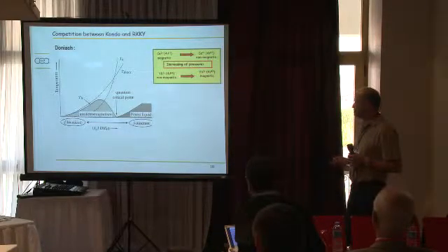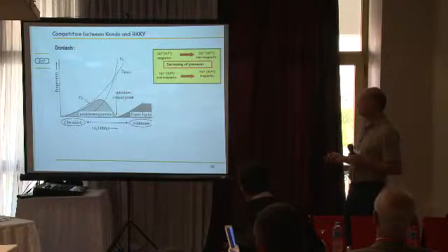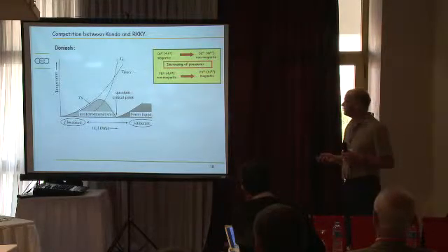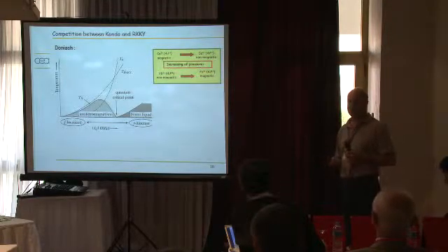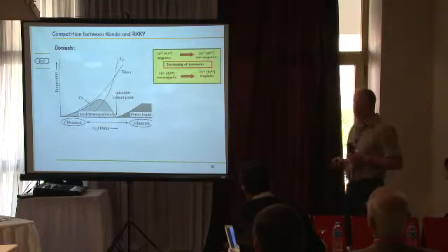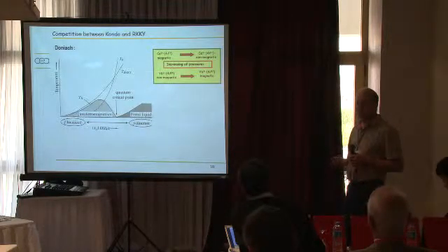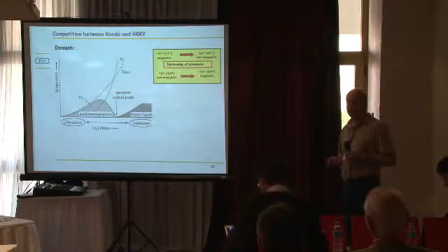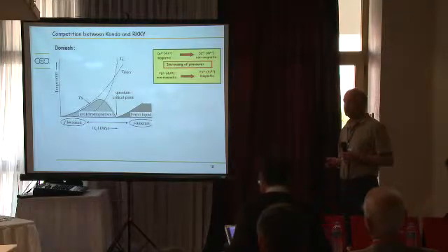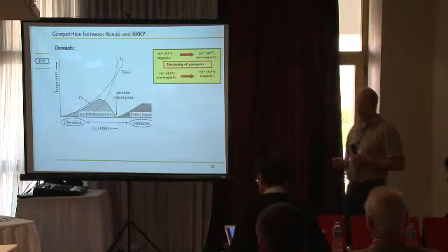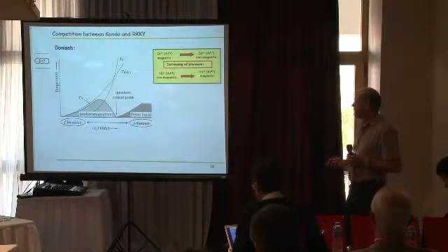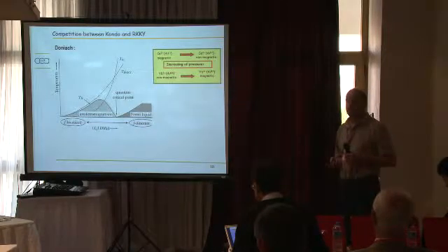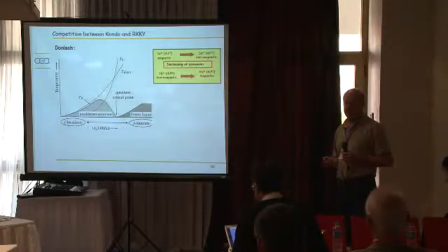Now you see that, strangely, I'm talking a different language to the original picture, because I'm not talking about valence changes anymore. In fact, if you read the original Doniach paper, he says very specifically that non-integer valence states are not taken into account. Now, this is obviously not true in heavy fermion systems, where these non-integer states are the basis for all the exotic properties. So how can we use this approach to describe what's happening in heavy fermion systems, and particularly in ytterbium?